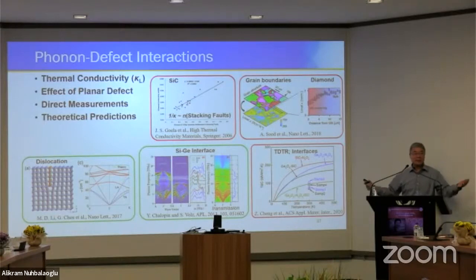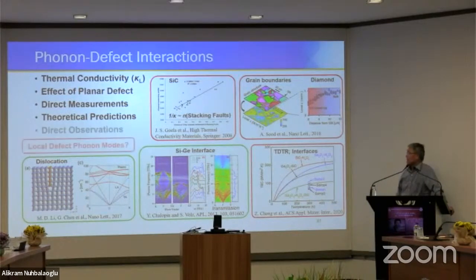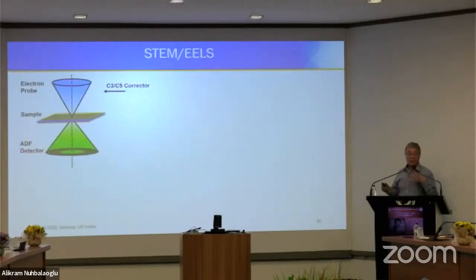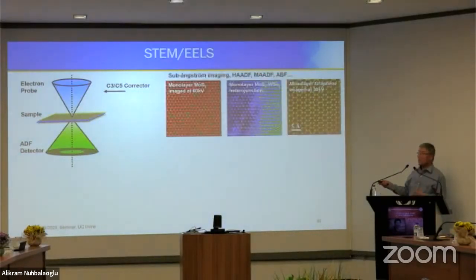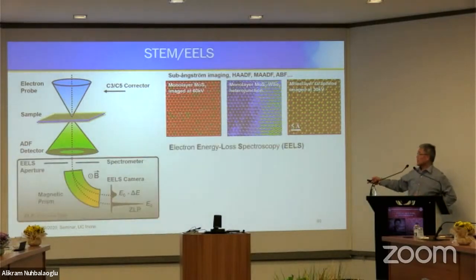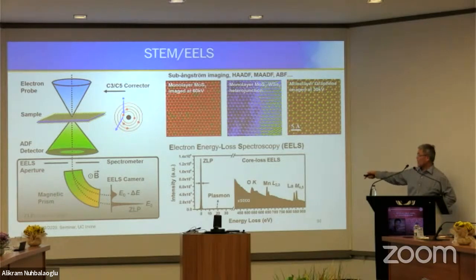Also at the interface, like the silicon germanium interface, a model system, shows that the interface between silicon germanium scatters phonons and then has low thermal conductivity, right? But there's no direct measurement, no local measurement. So electron microscopy developed. In addition to imaging, you can also analyze the functionality by using EELS. So EELS can be done in different ways. EELS is scattered by the valence electrons, the core electrons at the ionization energy. You can study the existence of the element in the material using core-loss.